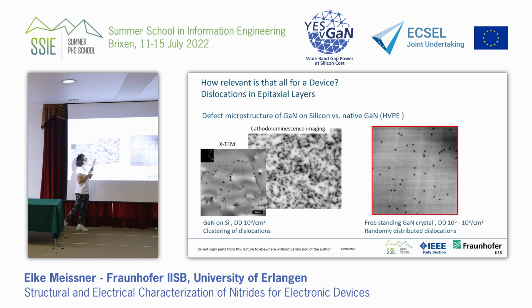So you have an uneven distribution. You have clusters, you have cell formation, you have places where you have no dislocations, you have alignments, for example. And here, in a native crystal, freestanding gallium nitride, you have 10 to the 5th or 10 to the 6th dislocations. It can also be 10 to the 4. If you have a ammonothermal material, you have 10 to the 4 dislocations, or even lower. And then you see that each of these points is a single dislocation. So you don't have clusters or alignments. And this is all fortunate for the device. This shows this is the physical way to go.